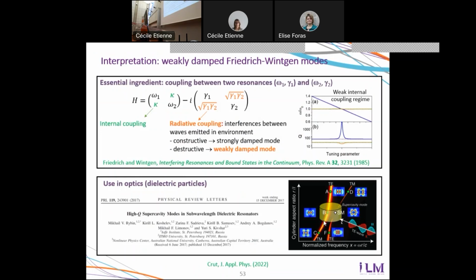When interferences are constructive, it means that the wave is reinforced. We have more acoustic radiation, and therefore we have a more strongly damped mode. But interferences can also be destructive, in which case the amplitude of the emitted wave in the substrate is reduced, meaning that the vibrations remain more localized in the object. So it's what happens in our experiments, and it's also a very general phenomenon that is not restricted to the acoustics field. You have similar manifestations of this phenomenon in optics, which were described first in this paper in 2017, showing that this effect can be used to make dielectric resonators with very high quality factors.